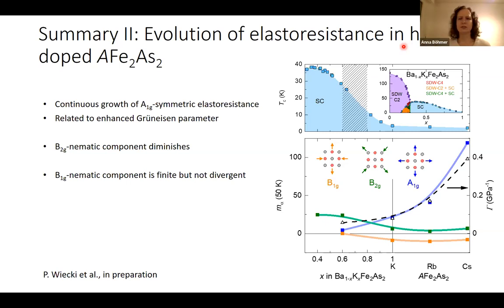Okay, I think there's two components. No, the theoretical modeling did not take that into account. When you talk about magnetic moments, I think the role of nickel in this 114 is just the same as nickel in the 122s, and that was studied quite in detail. It is an impurity. We see an enhanced residual resistance. We see enhanced scattering. There's no magnetic moments there. It's an impurity in the iron plane, so it's quite significant, but there's no extra magnetic moments. I see. Okay, thank you.